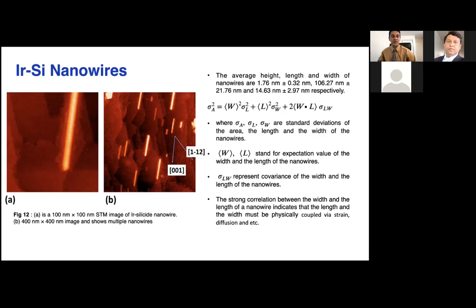Then after that, we wanted to see if there is any relationship between the length and the width of the nanowire. To do that, we did some statistical analysis. From the statistical analysis, we found that there's a strong correlation between the length and the width of the nanowires, which means that they are physically coupled via strain and diffusion, which means that we can change the length and the width of the nanowires by providing the ideal thermodynamic environment. Okay, that is the dimension analysis of the nanowires.